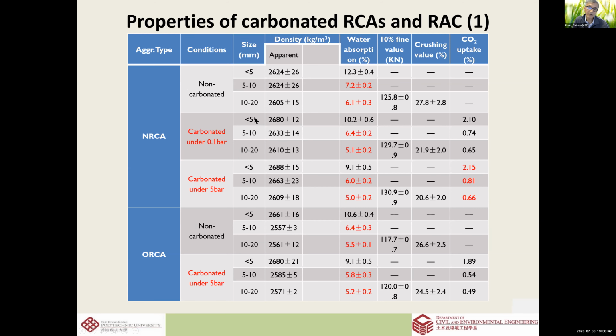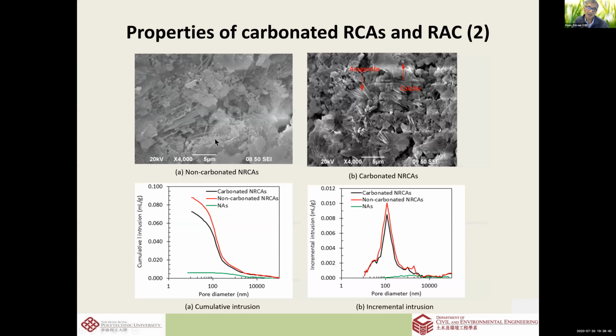And then this is before carbonation. We can see there are a lot of the normal hydrated phases: calcium silicate, calcium hydroxide, AFt, the ettringite phase, calcium silicate hydrate. But after carbonation, we can see the calcium carbonate phases, like the calcite phase, and aragonite is another crystal phase of the calcium carbonate, and then the pore structure has also been changed. This is natural aggregate, this is the uncarbonated, this is carbonated. So the pore is densified with the carbonation.